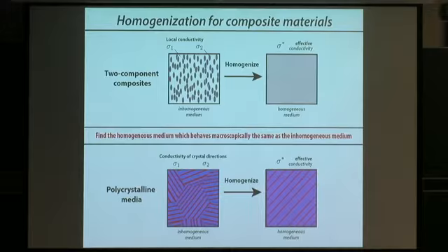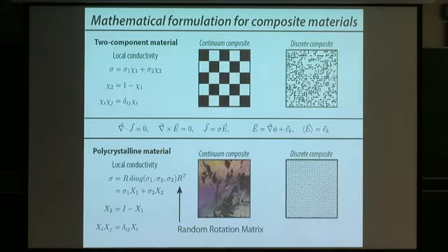Okay, namely here's homogenization for the two-phase conducting problem, same picture that you've seen before. Now we have all these individual crystals with a particular orientation, and we might have statistical information on the orientation of the individual crystals. We homogenize that to get an effective conductivity tensor to represent the whole polycrystalline material. There's some really interesting math here in that, through some clever manipulations, we can carry that whole framework that I just showed you over to the polycrystal problem.